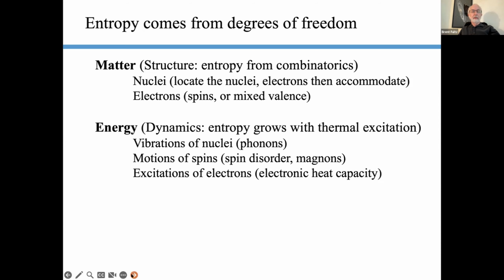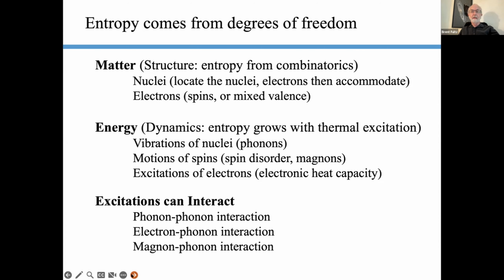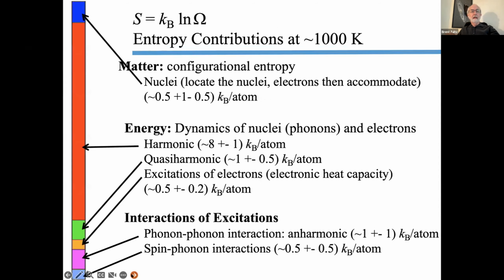This is all textbook stuff, but the thing that's tricky is that these excitations interact with each other, and the energy cost to put in another phonon when a lot of others are present and the atoms are displaced, that varies with temperature, for example. And likewise, the energy to put in a spin excitation varies with how many phonons are present too. So we have these other interactions we have to take into account. Here's the big scale. The combinations of atoms on a lattice are up here in the left at this 0.69 kB per atom. There are people now doing high entropy alloys where they can double or maybe almost triple this.